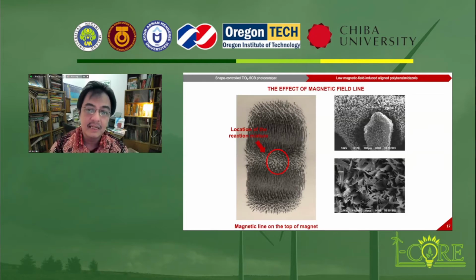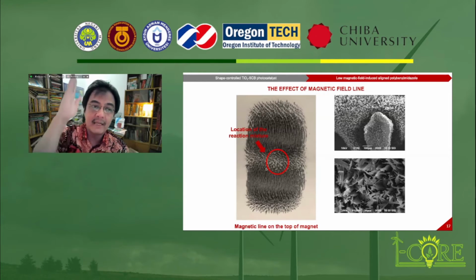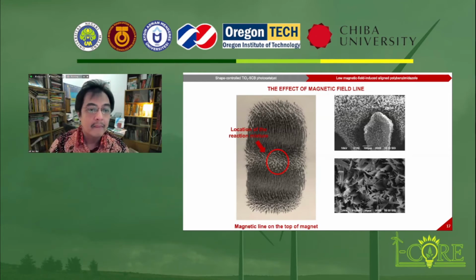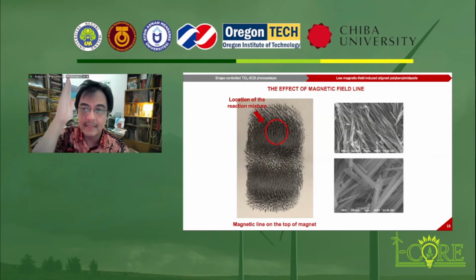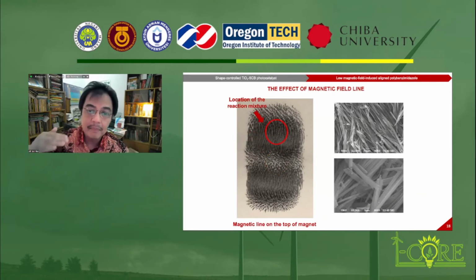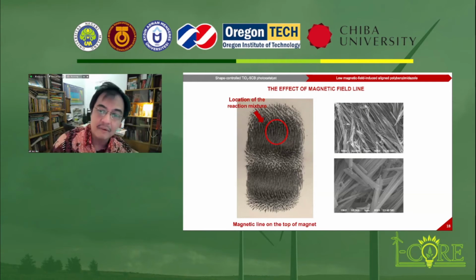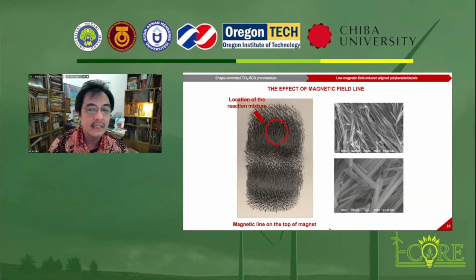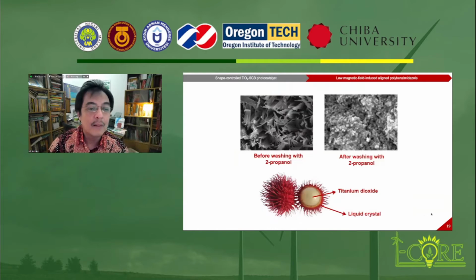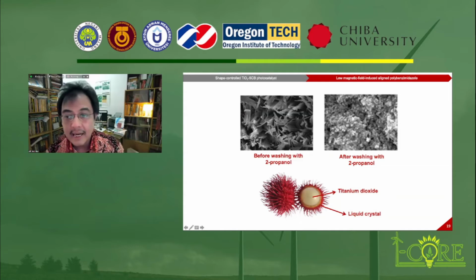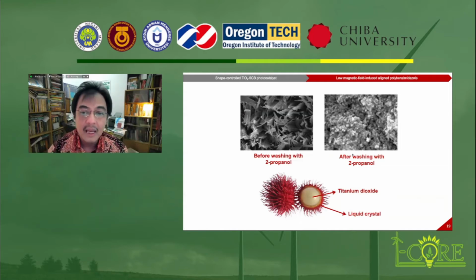This is the result of the sample placed on top of the magnet in the through-plane direction. And we found an interesting result: if we put the sample in the in-plane direction of the magnetic field, we can see rambutan-like materials. The resulting sample is like a rambutan-like material, where the hair of the rambutan is the liquid crystal, and the fruit is the titanium dioxide.